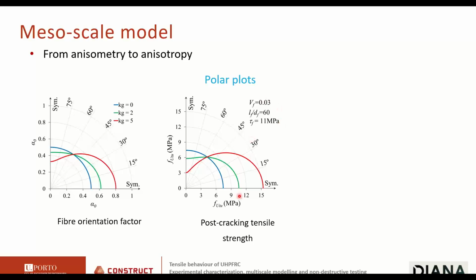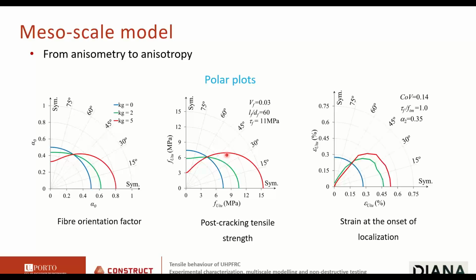Applying our equation for the tensile strength, we can go from here to the tensile strength. Applying the model that I have described, we even can get the strain at the onset of localization in every direction. Okay, we can describe the anisotropic behavior of the material if the fiber orientation is relevant.